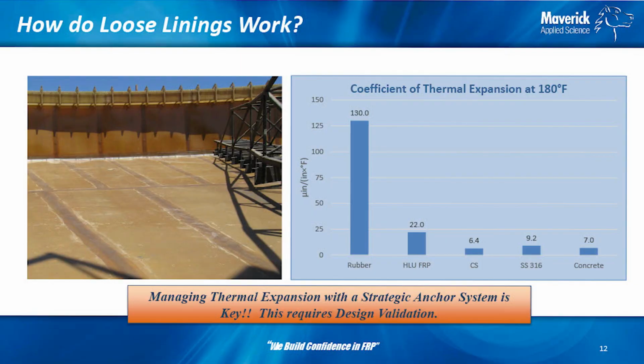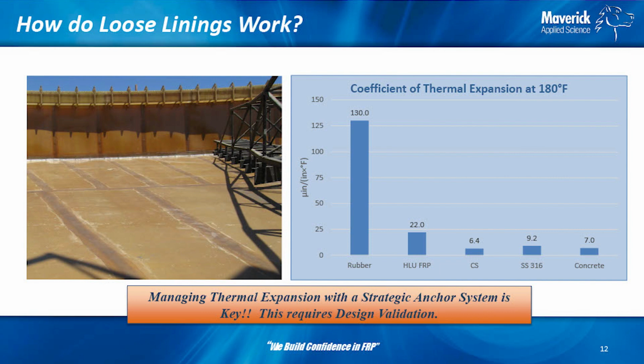You've already talked about some aspects of non-metallics, and we've talked about thermoplastics, and thermosets like FRP, and thermal expansion always comes up in the discussion pretty quickly. To give you an idea, we were looking at the coefficient of thermal expansion, in micro-inch per inch per degree Fahrenheit. So you have rubber here, and not surprisingly it's going to expand and contract quite a bit. So you've got 130. Here's hand layup FRP, and again, this is a process material. This tends to be very resin rich, about 60% resin to 40% glass. That resin is what drives thermal expansion. The more glass we have in it, we start to see that coefficient come back.